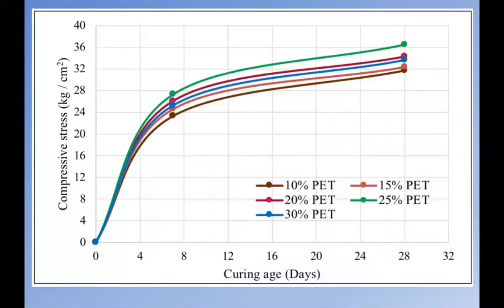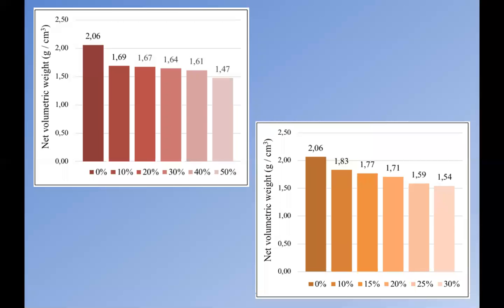In the case of volumetric weight, the specimens of the first test yielded a certain similarity between the percentages of 10, 20, and 30% PET. The obtained values are reduced while increasing the amount of PET plastic. The lowest values corresponded to the blocks between 25% and 30% PET plus nanoadditive, compared to the volumetric weight obtained in the blocks made without plastic additive.